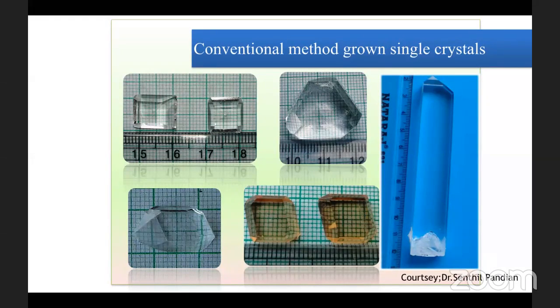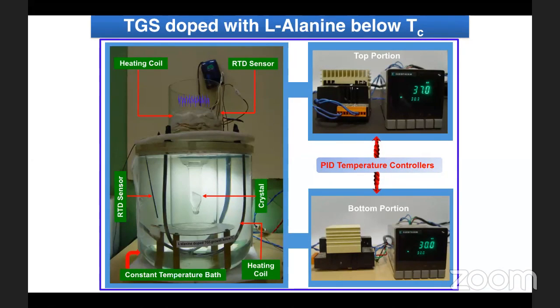Using the seed rotation method, we have grown these big size crystals. These are KDP crystals, so you can use them for laser applications. And also this is a crystal from the SR method of growth. This is triglycine sulfate doped with L-Alanine, which is grown by Dr. Senthil Pandian. They maintained different zone temperatures here. Here is a lower temperature, here is a higher temperature. Due to the higher temperature, the solution gets evaporated, and then solid starts to grow at the bottom where you have a seed.